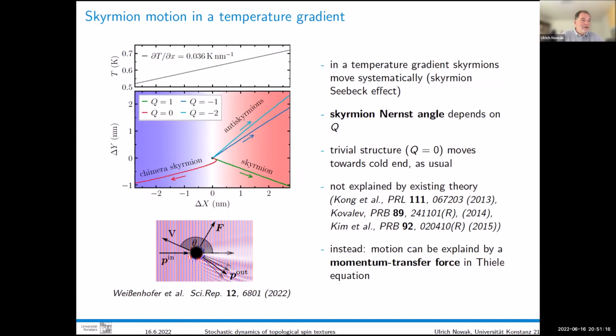And to make a long story short, how that works is explained in this graph. That can be understood by a momentum transfer. The temperature gradient creates a magnon current. So assume there are magnons now going from the hot to the cold end. They are moving, then they are scattered. Because of this scattering of the magnons at this skyrmion, we get a force that points in some direction. And because the Thiele equation has this cross product term, the resulting velocity is perpendicular to the force. That explains the strange angle. So it depends on the scattering potential of the skyrmion and the scattering direction. You get this effective motion that can indeed point against the magnon current.